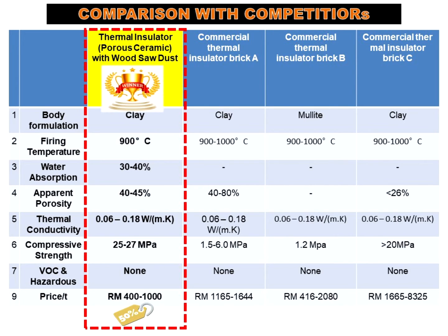Well, why are we confident that the Green PCTI can be well accepted by the building and construction industry? To answer this, let us look at the technical specifications and price comparisons between the Green PCTI and commercial thermal insulator. Based on the technical comparisons, the Green PCTI is an overall winner in terms of lower thermal conductivity, higher compressive strength, comparable porosity, zero VOC, non-hazardous, recyclable, as well as lower firing temperature for energy efficiency in production. Overall, it is also among the cheapest, as the pore forming agent is a waste material, which is the wood sawdust waste.